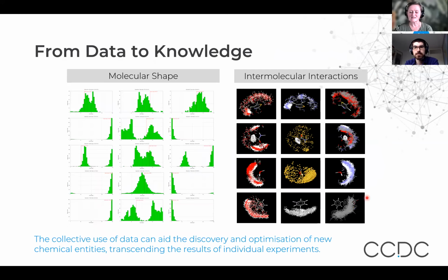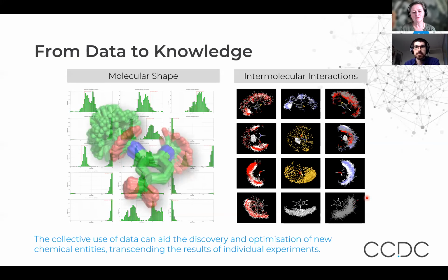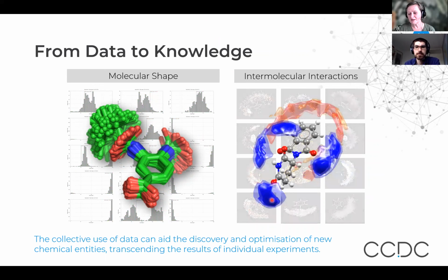And so when we start pairing this information, when we start looking at the entire embodiment of the Cambridge Structure Database, now we start to get unique insights that any one single crystal structure, much as Olga Kennard had envisioned, will afford us. So for example, we can look at isolated torsion angles and the distribution of those torsion angles. And collectively across all of the flexible rotatable bonds, we can start to tease out what likely molecular conformations a molecule will adopt. Likewise, when we look at interactions to isolated interacting, for example, hydrogen bonding sites, we can superpose those on the molecule of interest to understand what in this representation might be a hydrogen bonding environment.